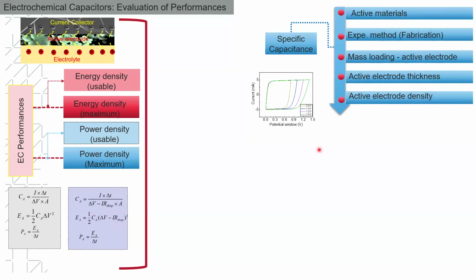So what are the parameters when you want to fabricate a supercapacitor? What are the major things you want to check for specific capacitance enhancement? Is it the active material which you are going to use, and the method of fabrication which you are going to implement? For example, if you are planning to develop a thin film or a thick film, the mass loading of the active material changes, and you can see there is a strong influence. Depending on your type of application or implementation, you can use different types of material, and the specific capacitance depends purely on the influence of these materials.